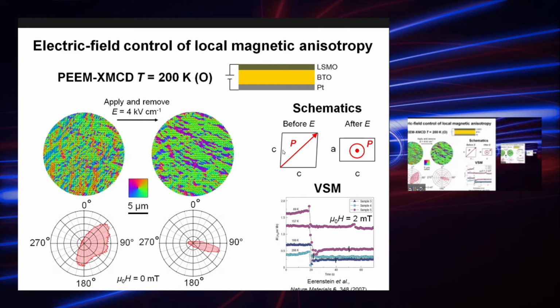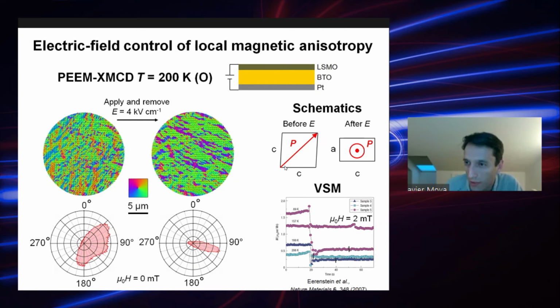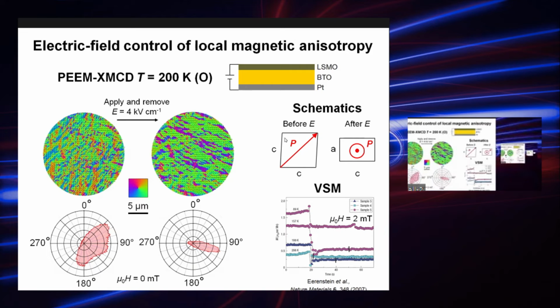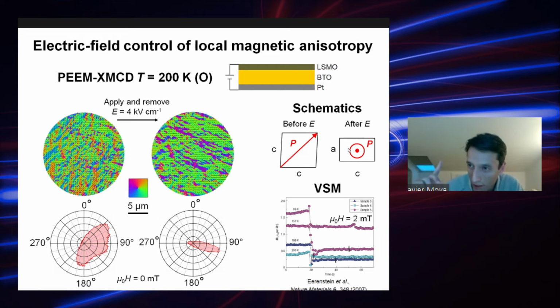So initially the substrate is showing this strain configuration to the film. It's almost a square unit cell. So this is why the material is primarily biaxial, because it can be pointing in all directions. And then when you see the polarization out of plane, the strain template that the substrate is presenting to the film is like a rectangle. And again, when it's a rectangle, the polarization is going to align along the longer direction.